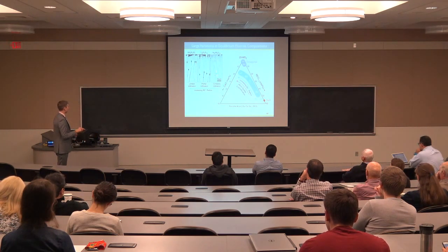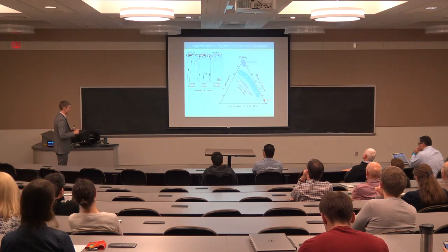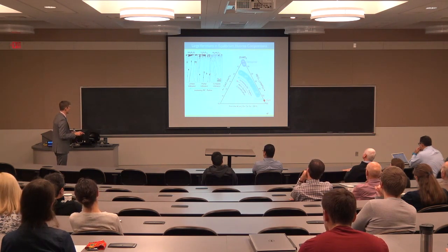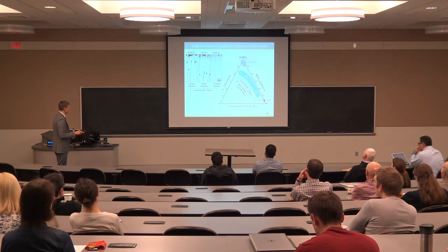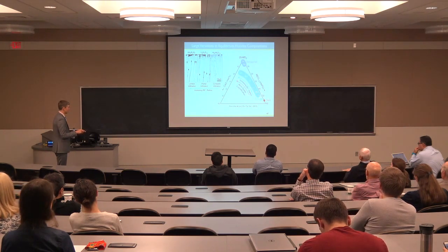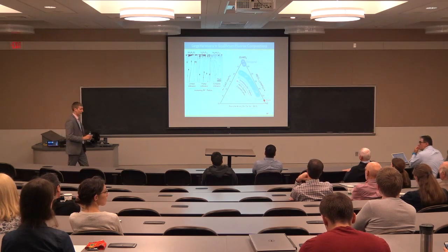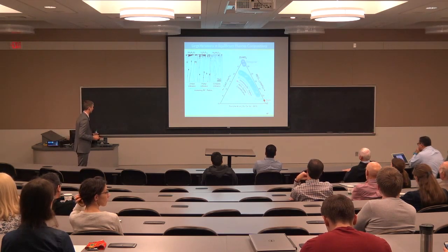And this directly explains the difference that we see between the gadolinium system, that falls sort of in the middle in terms of behavior and in terms of rare earth cation size, and these other systems that perform less well in this context. The yttria performs particularly poorly, and that's because the difference in the fluoride composition between where we start and the fluoride we form is very small, so we can't form much apatite in that system.